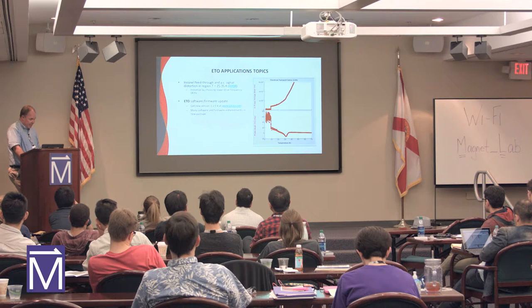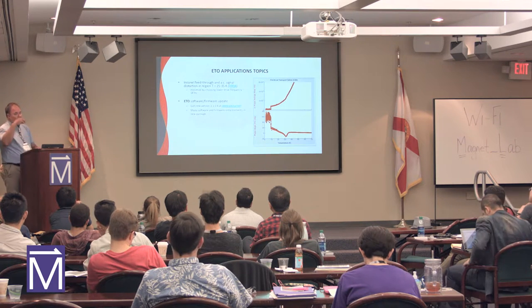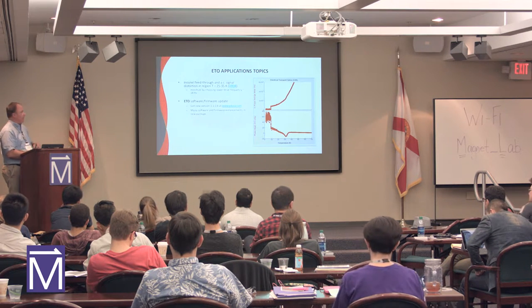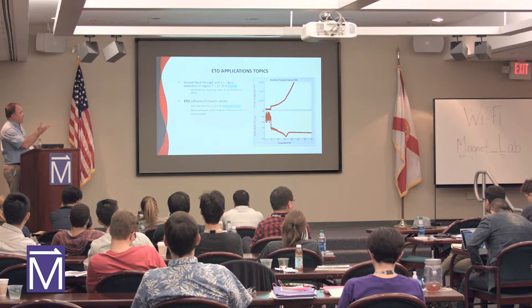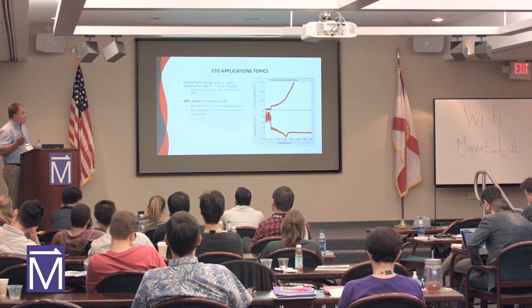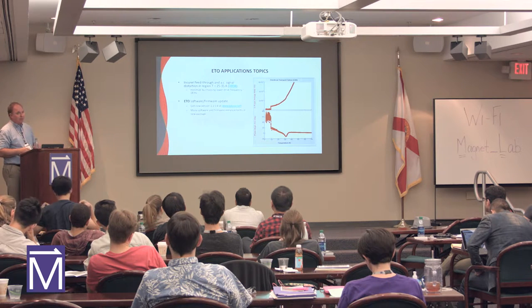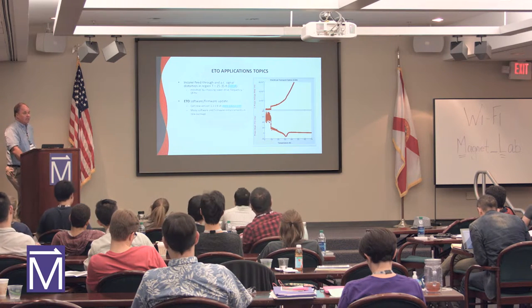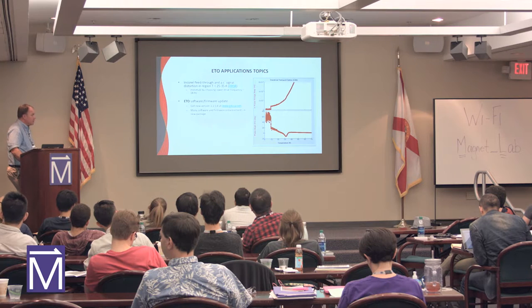You can't get away with it because you need to use these feed-throughs in the low temperature physics, right? You need these feed-throughs to keep things at low temperature. So you buy these things, you have the wires going through them, but they may introduce artifacts into your measurement. They're low frequency, in the 25 to 35K region. So if you see an artifact in that region, it may not be due to your data. It may be due to the feed-throughs. And we've got an application note that describes the physics behind what's happening on that. And then there are some software updates that look for this.